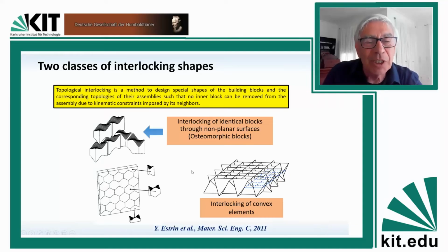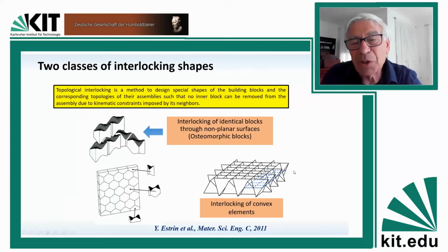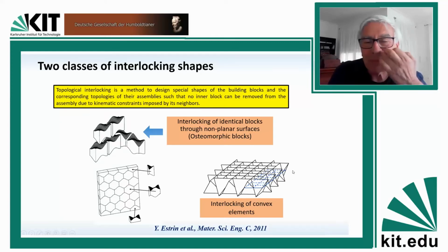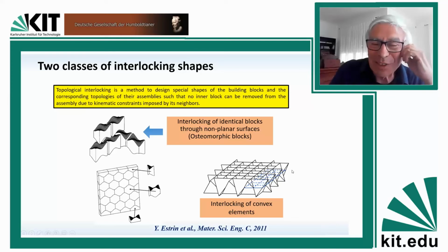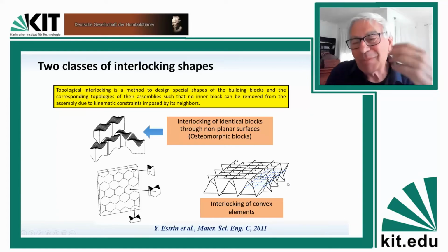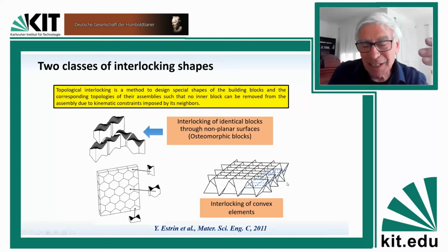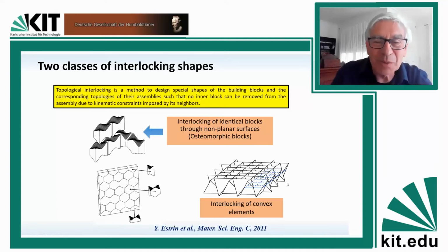They're interlocked in the structure topologically or geometrically, but we can also have another family of blocks which are convex polyhedra, like tetrahedra here. And if you stack them in this way, it can be shown that you cannot move an element out of the structure, apart from the elements at the periphery. So you have to fix them somehow. But those which have the right neighborhood are arrested within the structure.